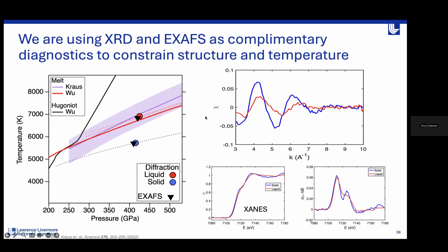Now, unfortunately, this isn't the part of the talk where I give you a temperature constraint of the iron melt curve - this is work that is ongoing. In order to infer the temperature from our XAFS data, we have to do a series of QMD runs where we're simulating iron XAFS at a series of temperatures and densities, and then comparing them to our data that we've collected here.